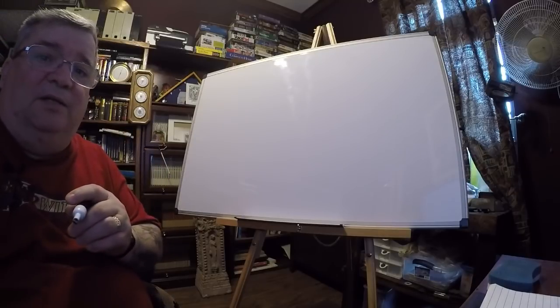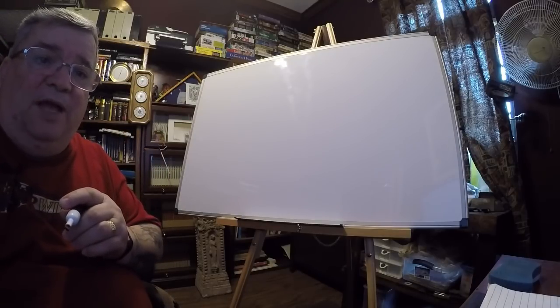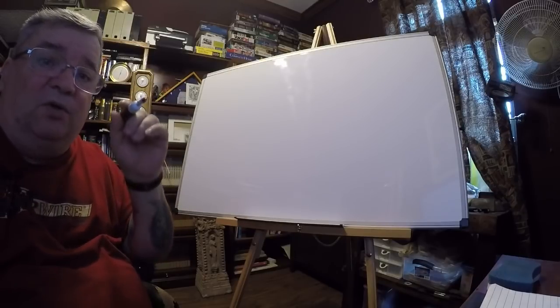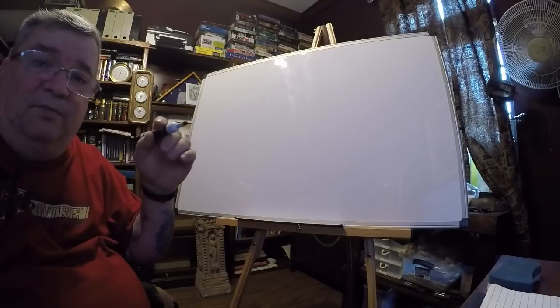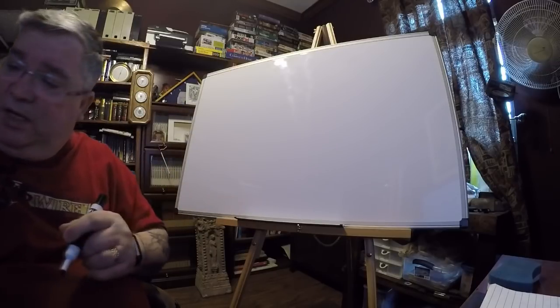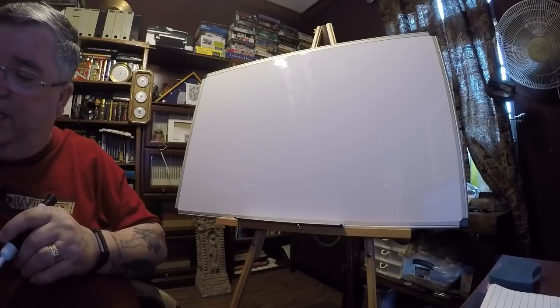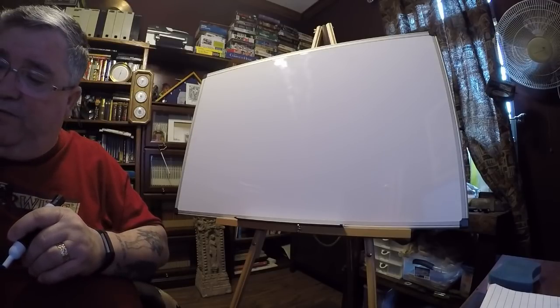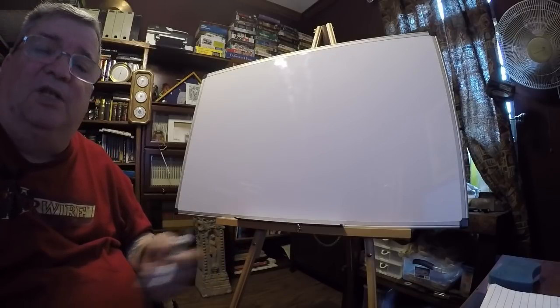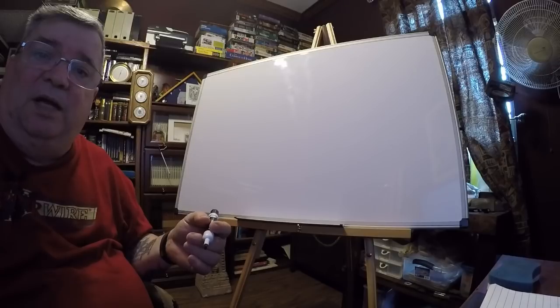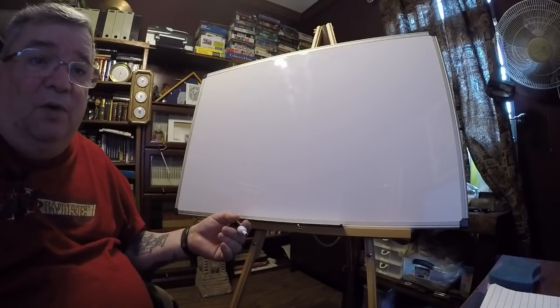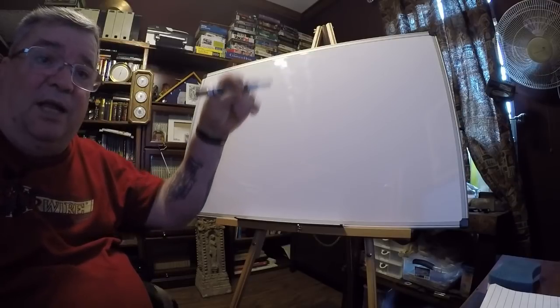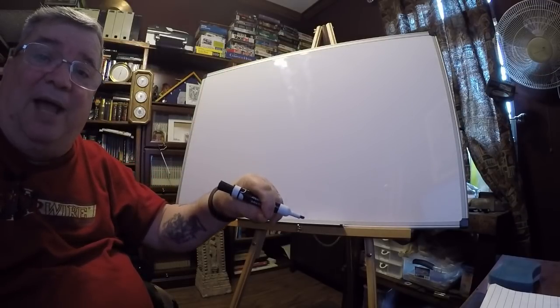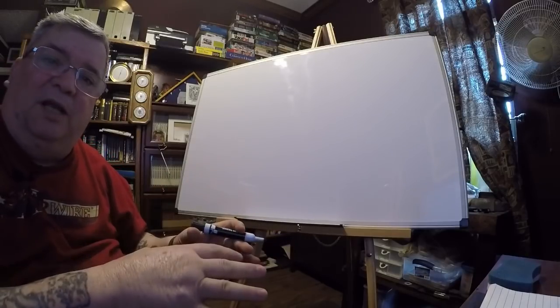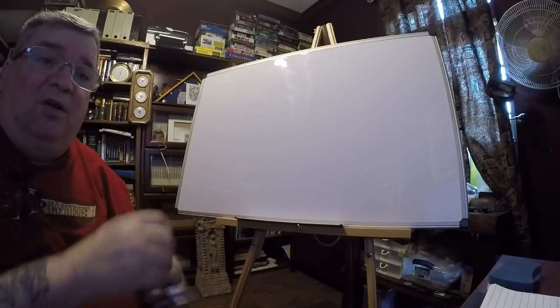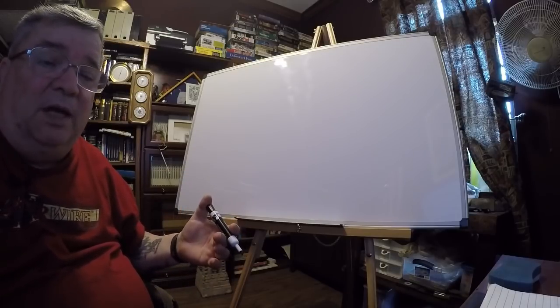That's why I got into all that, because I wanted to tell you that you don't just tin the inside of the bearing shell, you also tin the outside perimeter, the periphery, and why you had to do that. So now we're going to get back to the original subject of tinning the shell. You don't necessarily want the entire shell with a layer of tin on it, though if you were to dip it in a flux and then into a tin bath, a pot of molten tin, you're going to have a nice layer of tin all the way around, which couldn't hurt.